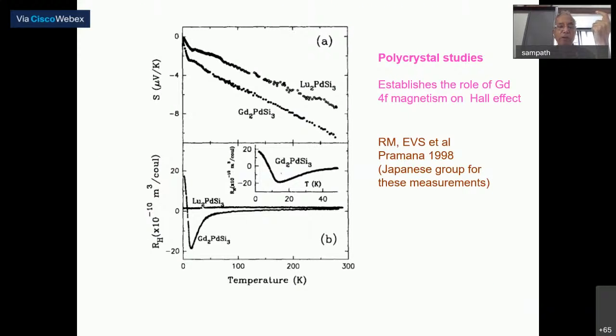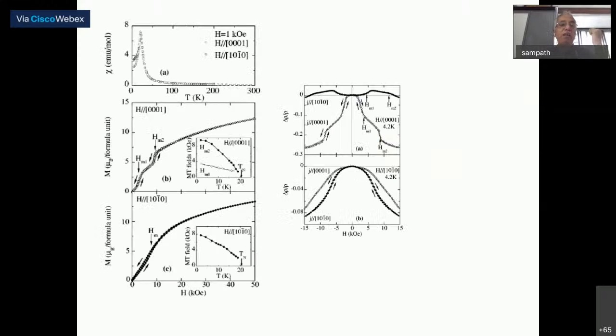So therefore, we then measured the Hall effect, and you will find that there is a sign reversal here. All values are quite huge. Now, the initial indicators suggest that both antiferro and ferromagnetic correlations are present. Now, we measured the Hall effect on a single crystal. We saw something very, very exotic which was not known earlier.